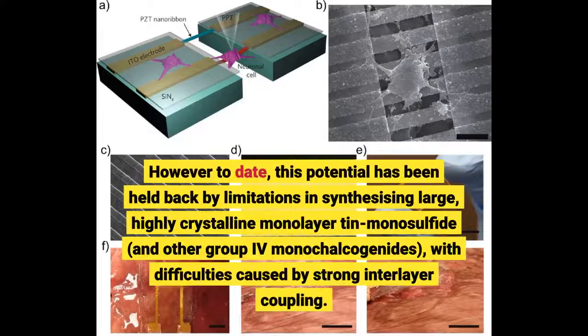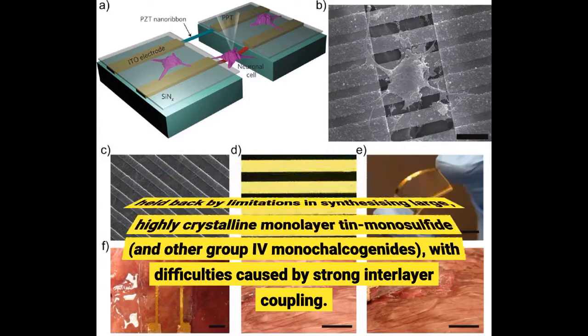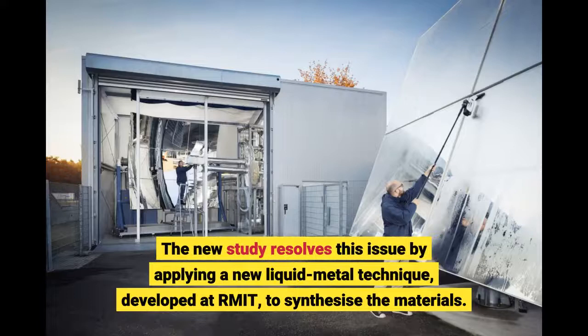However, to date, this potential has been held back by limitations in synthesizing large, highly crystalline monolayer tin-monosulfide and other group IV monochalcogenides, with difficulties caused by strong interlayer coupling. The new study resolves this issue by applying a new liquid metal technique, developed at RMIT, to synthesize the materials. Subsequent measurements confirm that tin monosulfide synthesized using the new method displays excellent electronic and piezoelectric properties.